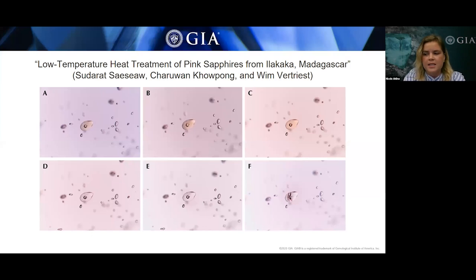And then if you look at box D, that's the monazite at 600 degrees. So it's already starting to become colorless. And then once you reach box F, which is now reaching about 1000 degrees, so you're coming up to that higher heat treatment, you're developing a very noticeable tension crack.